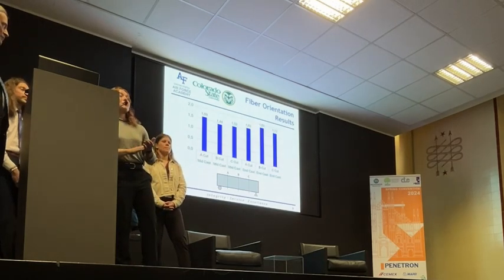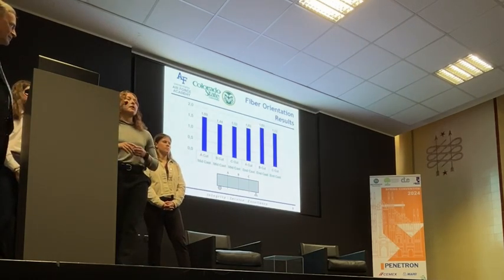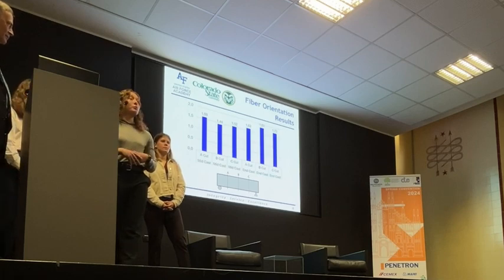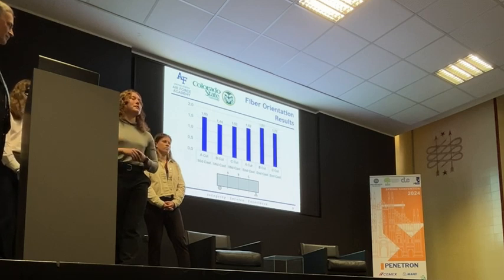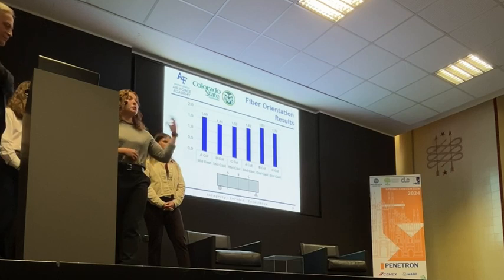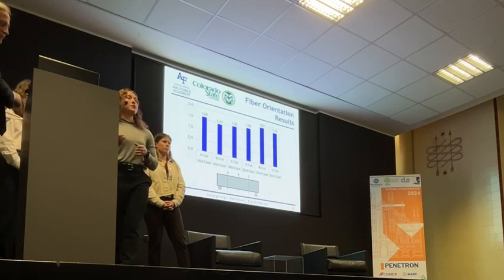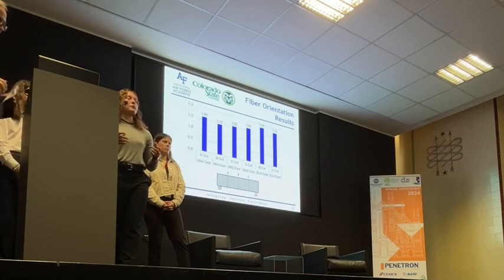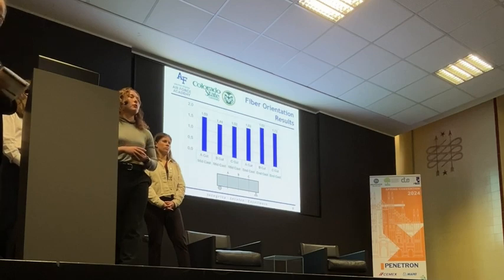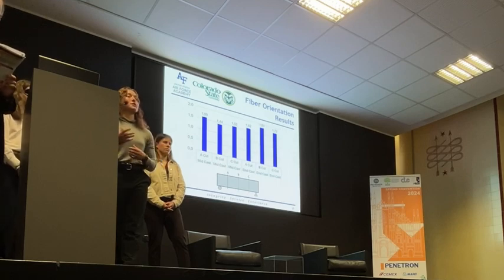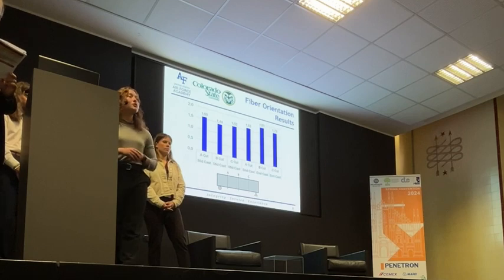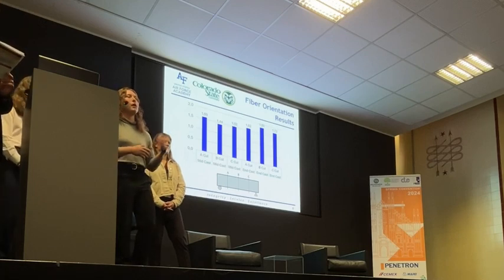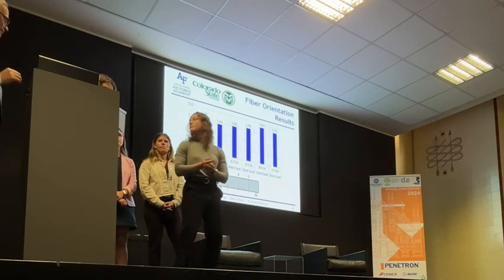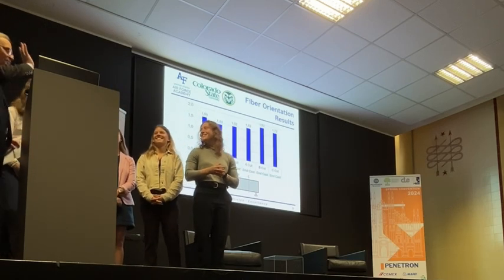Thank you. Yeah, so this isn't our first experiment with UHPC. We've been going at it for about 1.5 years now. From our own previous research, the one right before this, we varied volume fiber fraction from 2% on the higher end, and we also did one with 0.5% just to see if higher volume fiber fraction does a lot more for its overall performance. And we noticed that it didn't really have a significant difference between its performance with the 2% versus the 0.5%. And for financial and equipment constraints, it was better for us in the end to use 0.5%, and it still performed just as well. So it was based on previous research on why we chose the 0.5%. And it's a little more sustainable. Yeah, less steel. Well, thank you very much.